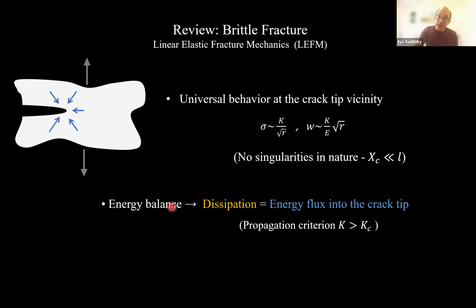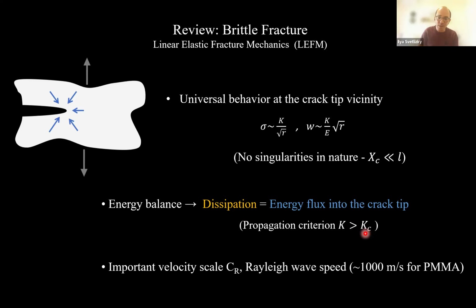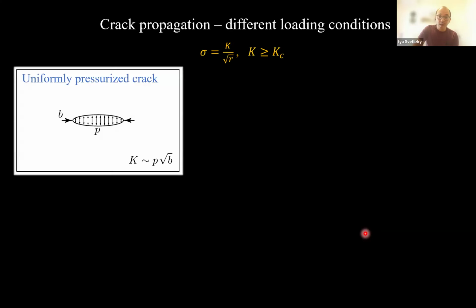You can rephrase this energy balance, saying that the crack will propagate only once the stress intensity factor K, the prefactor of your stresses, equals or exceeds Kc, the critical value, sometimes called the material toughness. Now, there is an important velocity scale. Typically, cracks accelerate and reach the Rayleigh wave speed, something like 1,000 meters per second for PMMA. This is the plastic that Thomas was using. So the behavior around the crack tip is universal. The prefactor K is not. It's determined by the specific geometry or loading conditions that you use.